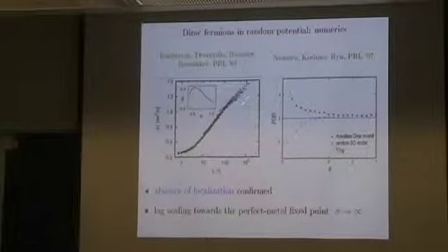And indeed, numerics shows that conductivity in this model is metallic, and it's super metallic in the sense that it flows logarithmically to infinity because it's symplectic class. Once the conductivity is big, then we know from the perturbative calculation that it should become still bigger. It's logarithmic, and it flows to what we call a super metal. It's infinite conductivity.